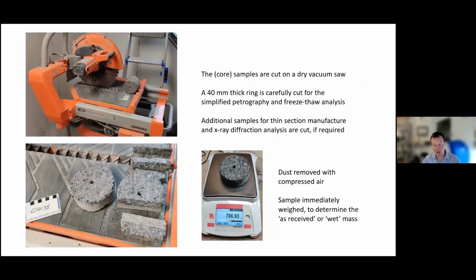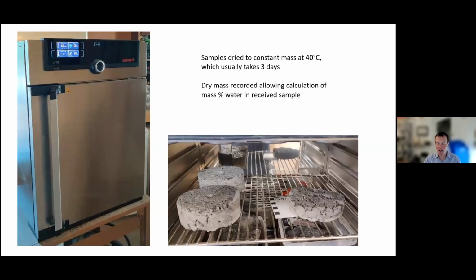The process I do, which is not the same as every lab, because each lab has their own thing, is to take a vacuum saw, which has a dry blade on it, and I carefully cut a 40 millimeter thick ring. I then blast it out with compressed air and I weigh it immediately. This gives me the as received mass of the concrete, so it's the concrete and the water it contains. I then dry it in an oven at 40 degrees centigrade until constant mass is achieved, which usually takes about 3 days. This allows the calculation of how much water is in the sample. And you'll see that water will become a key theme in my talk.